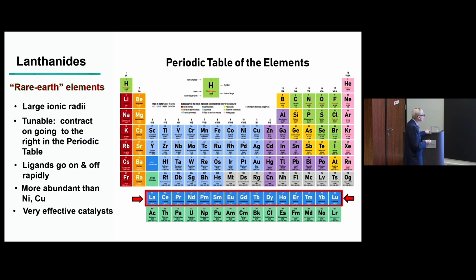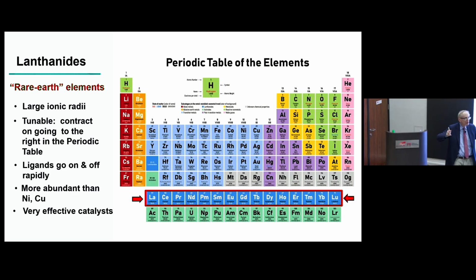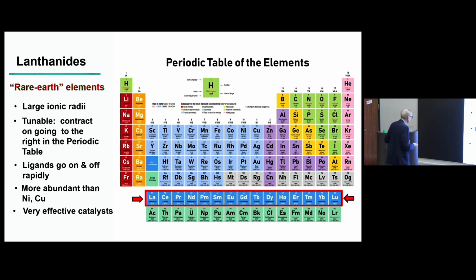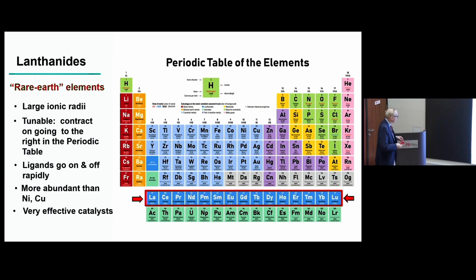They have very large ionic radii. I mean, it's like comparing a basketball to a softball in terms of ionic radii, and it's tunable. So as I cross the lanthanide series, it contracts, so I can pull the ligands in or push them away and change the chemistry. So ligands go on and off very rapidly, exactly what you want for a catalyst. And these metals are more abundant than nickel and copper, so they're really not rare. And they're very good catalysts.